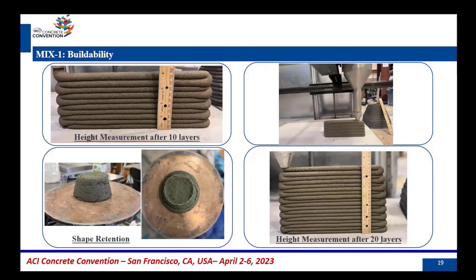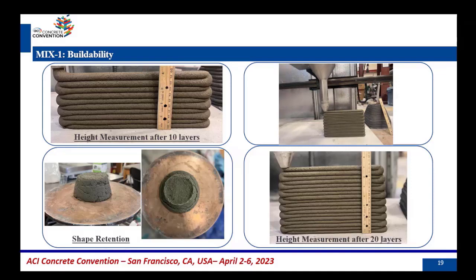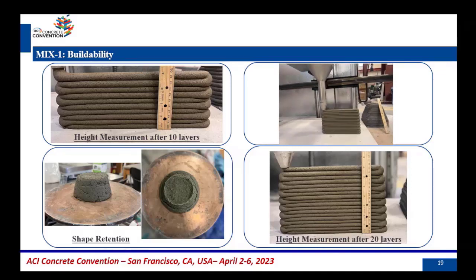For the buildability evaluation, we printed a wall, and we measured the total height of the wall, and also at 2 different intervals, like after printing 10 layers and after printing 20 layers. And this mix was buildable up to 20 layers. This was a single layered wall with a 20 millimeter dimension of the filament.